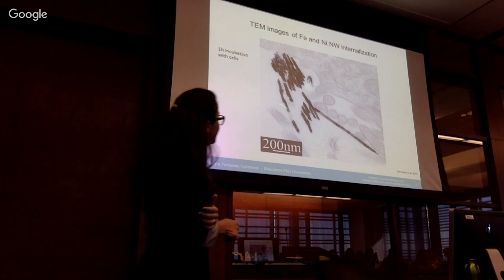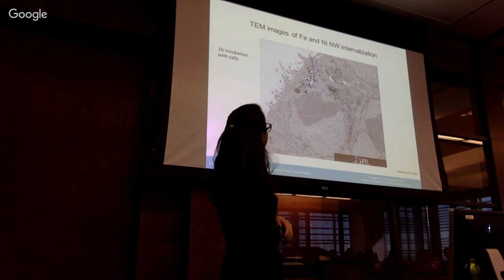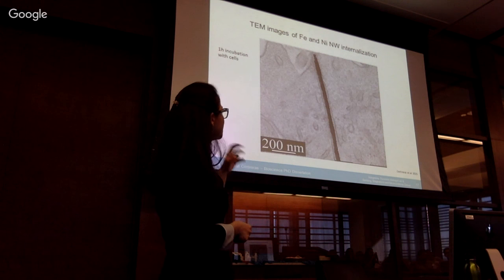When you incubate the wires for 1 hour, first I want to tell you that for both iron and nickel, the same processes were observed. So I'm not making any distinction here, because what I saw for one type of wires, I saw for the other. So this is a group of magnetic nanowires in touch with the apical side of the membrane, touching this kind of filopodia of the cell. This is another group of wires being internalized by the cells. And if I zoom in on these two areas, you can nicely see the membrane coating the wire. The wire is still engulfed and surrounded by a vesicle inside. And the same happened for this.